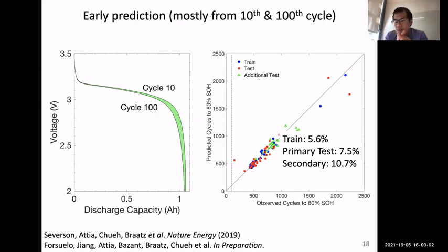And very surprisingly, when we did this and we developed an automatic featureization of this green area, we're able to develop a purely data-driven model that can map the early cycle performance of the battery between the 10th and the 100th cycle and correlate that to the total lifetime. So the plot on the right shows you the predicted lifetime and the observed lifetime using our data-driven approach. You can see we're able to achieve an accuracy exceeding 90%.